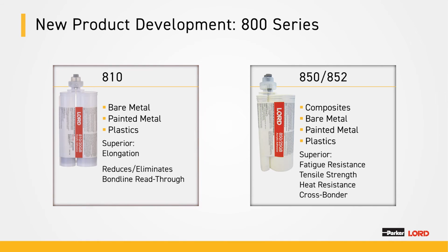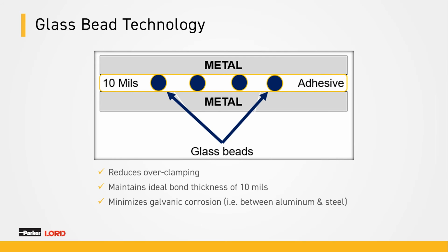between 2 materials. The Lord 850 and 852 is our next generation of acrylic bonding technology. These 2 products are a series or a product family. The 850 is faster and the 852 is slower in terms of cure. These were developed for a dump truck manufacturer, and they feature superior fatigue and temperature resistance, and it's our best cross bonder to date. In our studies, it has shown to bond very, very well to a wide range of substrates. Many of our acrylic products are equipped with glass beads.